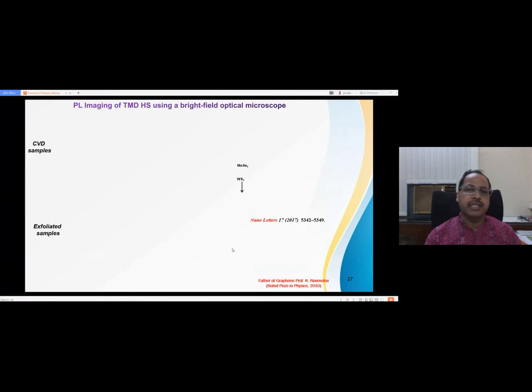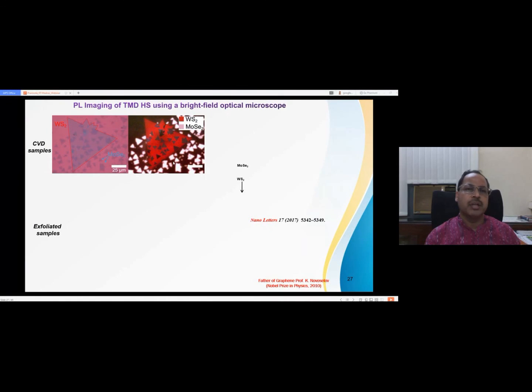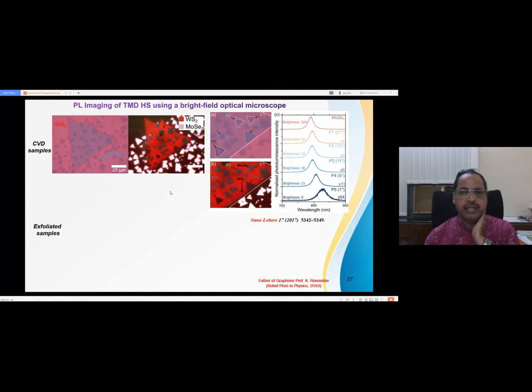So another technique we developed is called the PL imaging technique in the heterostructure, very simple. In the bright field optical microscope, you can take the imaging using bright field and dark field. So here you can see the CVD grown sample. The large area is WS2, and this is your molybdenum diselenide. And we do the imaging. And here you can see the zoom version of this figure.